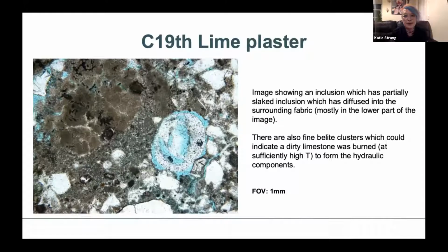But there are also fine belite clusters, and that would normally indicate a dirty limestone. So belite is a clinker component. It's a calcium silicate, and that forms through the hydraulic reaction that forms in a hydraulic lime. But because this clinker here is actually constrained to the lime inclusion, it's probably not having that much of an effect on the overall strength of the mortar.